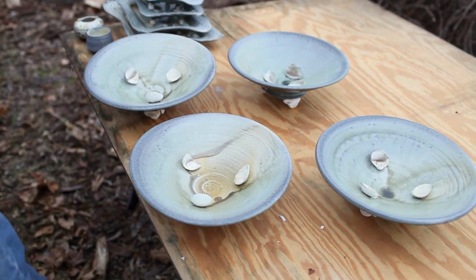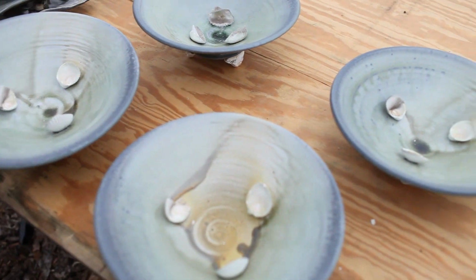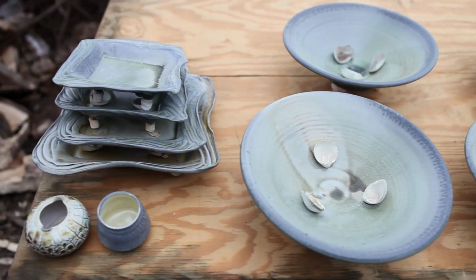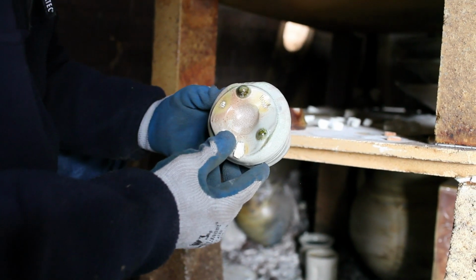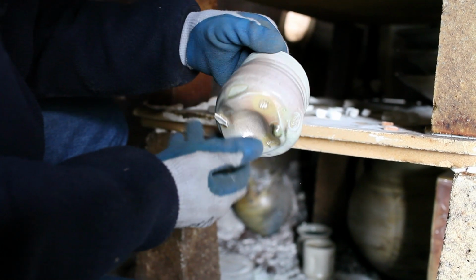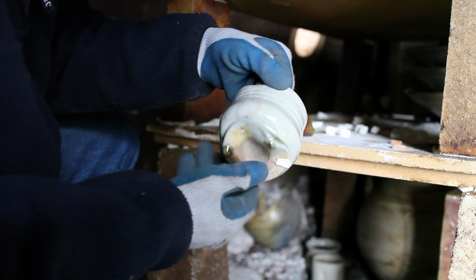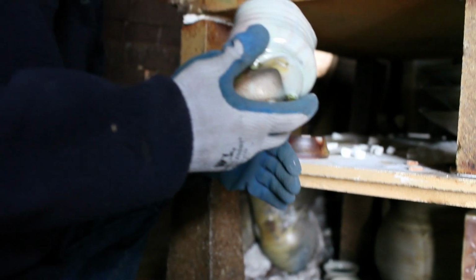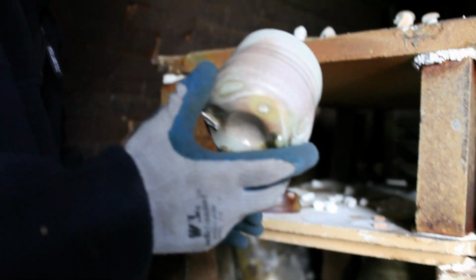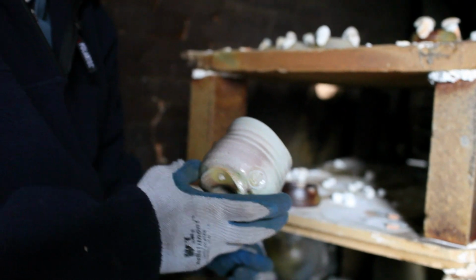It's a good clay body, boy. It's really good. That one is called flashing glass. I like that one. It's really good. I'm plugging away. That's nice. Yeah, isn't that lovely? So understated. Pastels are coming through. I've never seen pink out of a wood kiln before. I've gotten purple from an anagama, but that was about it. We got pink one time when we fired with molding, and they had some copper sprayed molding. It was a gold molding, but it had copper in it, and so we had pink throughout the kiln. Not just for that firing, but for the four firings. It just wouldn't go away.